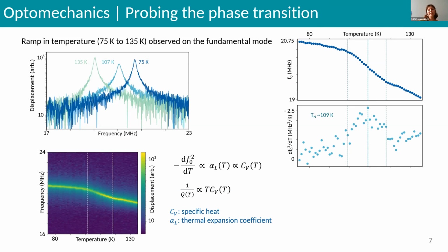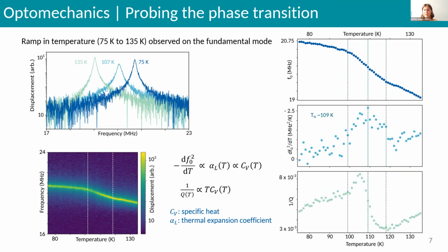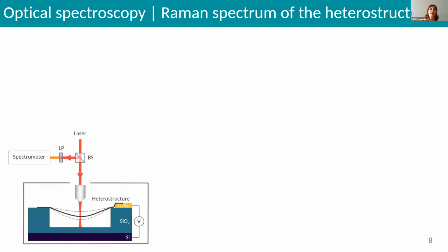You can also be interested in the quality factor, because the inverse of the quality factor is proportional to the temperature times the specific heat, and you then have an inflection point at the phase transition. So it confirms the result of another team on the same materials. For us, we have another technique to probe the phase transition, which is optical spectroscopy. On the same setup, we can do optical spectroscopy.